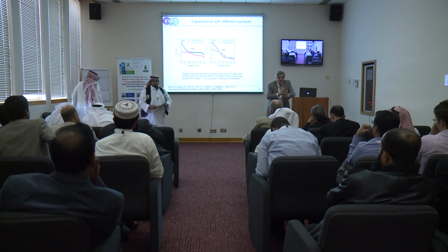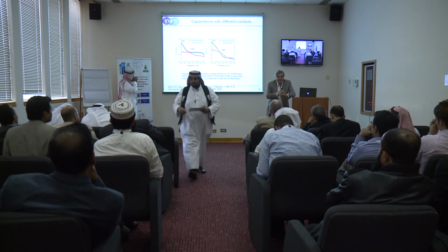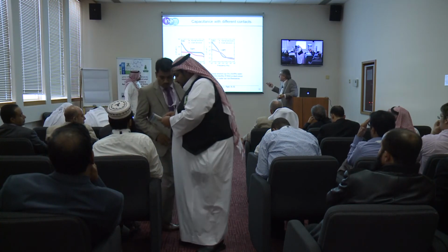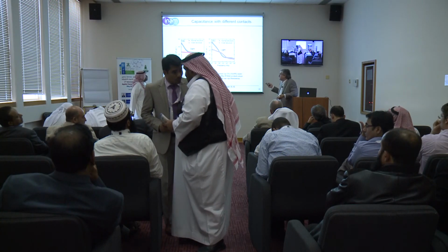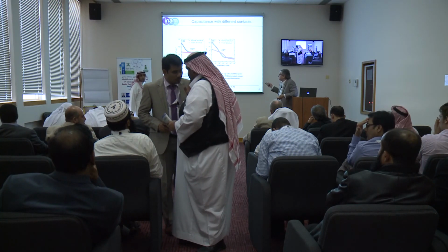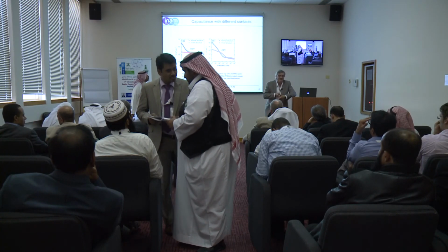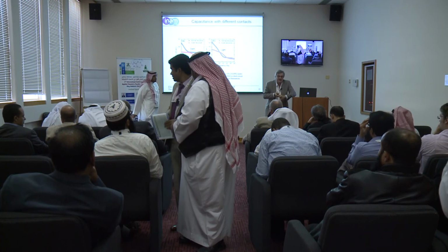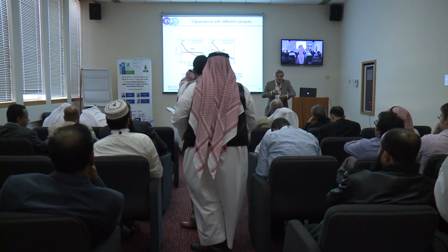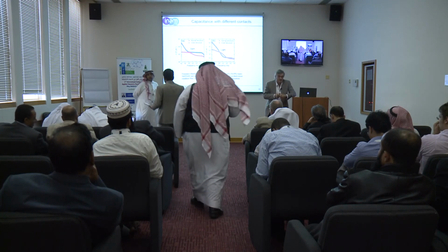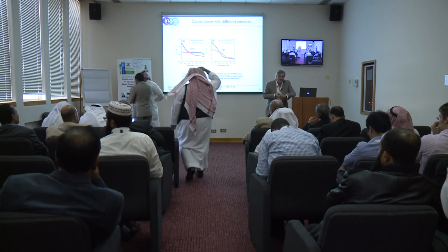Maybe the ions go a little bit inside, but the structure of the interface is very different. And in the light you can create some big capacitance in the two, but still we have two orders of magnitude difference. So I think this is very revealing that it's a contact phenomenon, this permanent hysteresis. And in fact, this modification must be that you are modifying somehow the barrier for injection. So this would be the key idea right now.